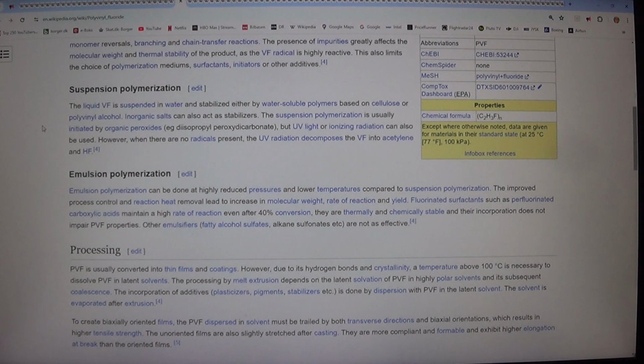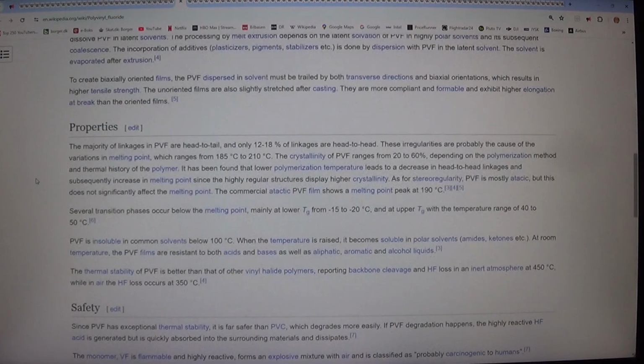Emulsion polymerization. Emulsion polymerization can be done at highly reduced pressures and lower temperatures compared to suspension polymerization. The improved process control and reaction heat removal lead to an increase in molecular weight, rate of reaction and yield. Fluorinated surfactants such as perfluorinated carboxylic acids maintain a high rate of reaction even after 40% conversion. They are thermally and chemically stable and their incorporation does not impair PVF properties. Other emulsifiers, fatty alcohol sulfates, alkane sulfonates etc., are not as effective.